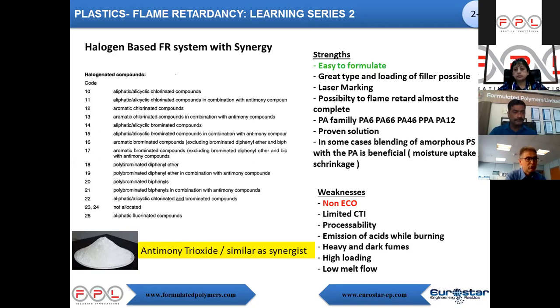Processability is sometimes a concern, but with new material, it's almost okay. When you go to real drawbacks, it is that when it's processed in overheating conditions, for example, it can release acids while burning. And acid is very corrosive to metals. And most of the time, when you are using a flame retardant plastic, it is to protect an electrical device. It can be a car or an electrical device. And the damage caused by the burning can go up to the connection, for example.